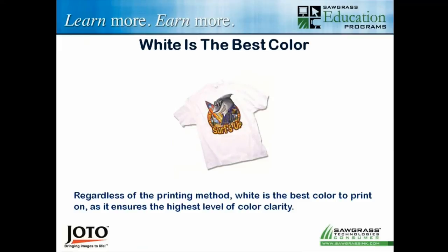The first one: it only works on white. The reality is that's not a rule, it's a guideline. White happens to be the best color — not just for sublimation, but for any form of printing, even screen printing. Sublimation is a dye process, so we're using a dye that's basically translucent or transparent by nature. It's very thin and goes into the fibers instead of onto the fibers. When we dye something, we're recoloring the fibers from the inside out, because of the way sublimation bonds internally with the molecular fibers of polymers and polyesters.